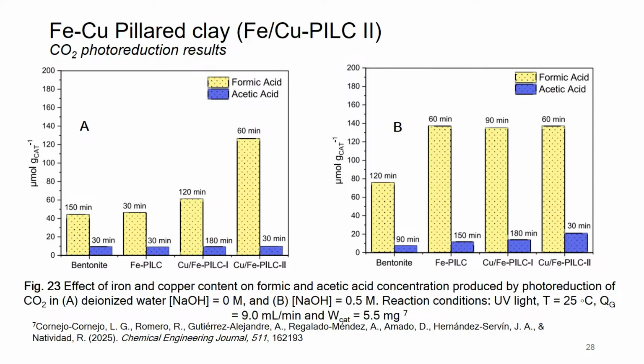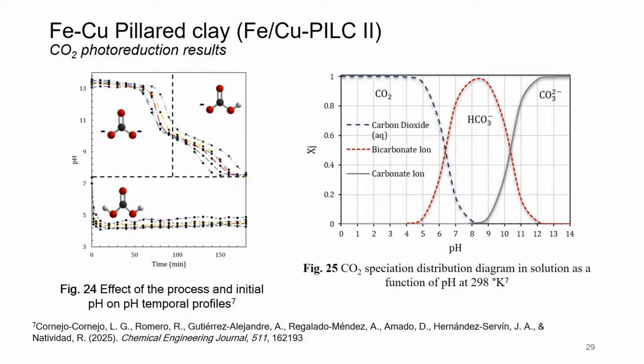So again, the higher the content of copper, the higher the formic acid. And also, you can observe here that when you use the sodium hydroxide, there is actually not much difference between these catalysts, but there is an important difference when there is only water. And as I told you before, this has to do with the speciation in the solution, where between a pH of 5 and 11, you have mainly the bicarbonate ion.